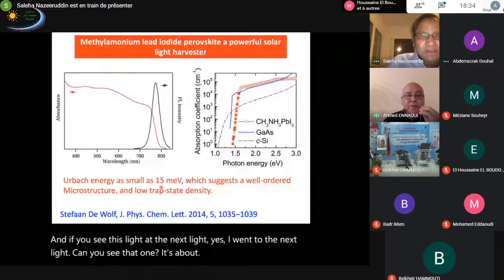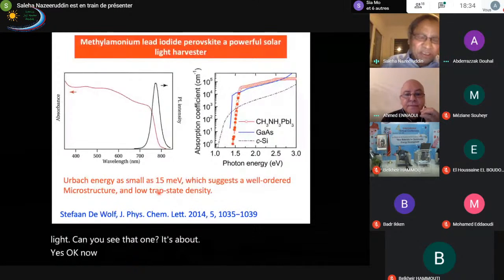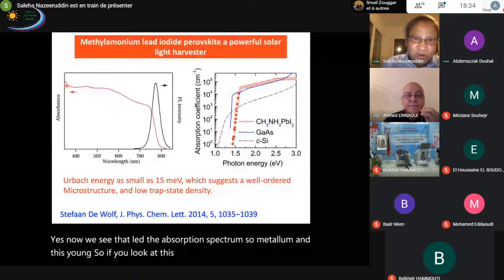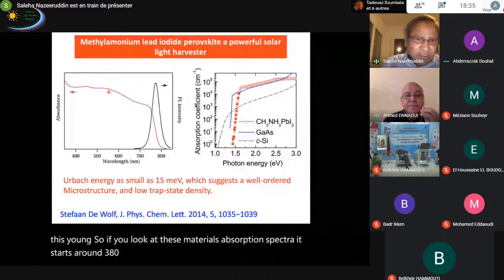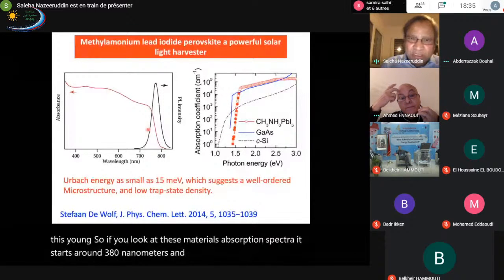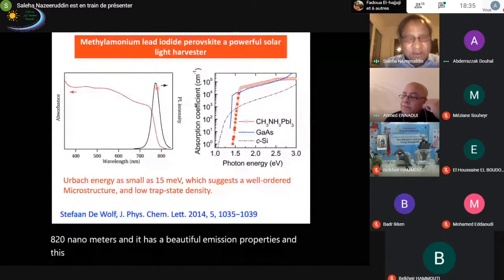Now we see the absorption spectra. If you look at this material's absorption spectra, it starts around 380 nanometers and absorbs all the way up to 820 nanometers. It also has beautiful emission properties, which we can make use of for both applications. When you shine light and extract the charges, it works as a solar cell; when you inject the carriers, electrons and positive charges, it gives you luminescence. So these materials have dual applications, solar cells as well as light emitting applications. There is a huge research effort going on in these two areas.